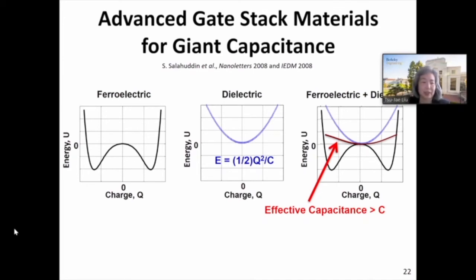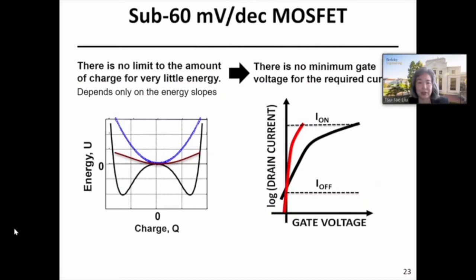So let me explain a little bit here. If you look at the energy versus charge for a ferroelectric capacitor versus a dielectric capacitor, they look different. Okay. But if you add them in series, you can actually end up with something like this. So this curve showing energy versus charge stored is flatter, and that's effectively getting a larger capacitance. So you get better capacitive coupling between the gate and the semiconductor channel region. And in principle, if you perfectly match the energy versus charge characteristics of the ferroelectric layer and the dielectric layer, you can get a nearly flat curve.